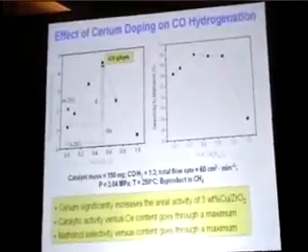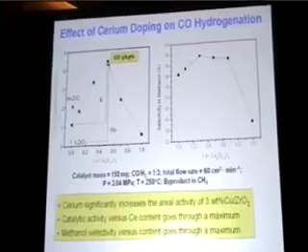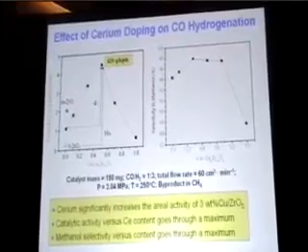This catalyst also gives you high selectivity. We're up at about 98% peak selectivity, which is also very good. The only byproduct is methane. There are no other alcohols. So we've looked a little bit at what is going on here.